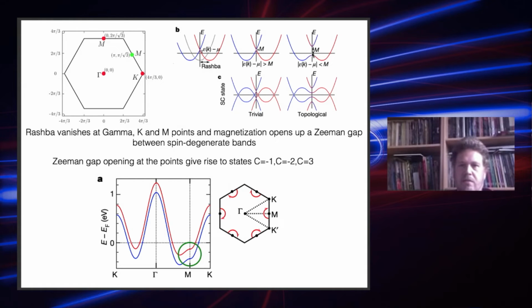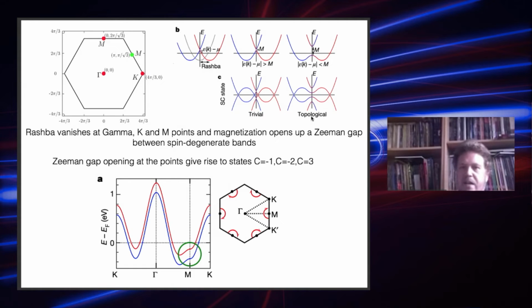And of course, this is the generic recipe of topological superconductivity. So if you have your chemical potential in the band gap, then when you induce superconductivity, you have a topological superconductor with this type of dispersion relation. This generic mechanism of having a Rashba coupling plus magnetization plus s-type pairing symmetry has been known since the pioneering works of a couple of groups 10 years ago to be really the paradigmatic ingredients of topological superconductivity.